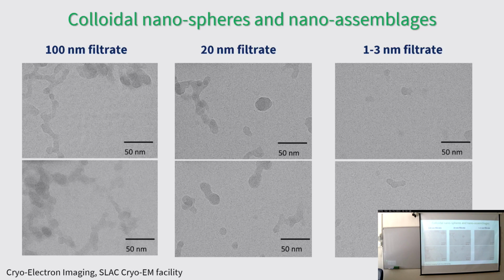Okay. So we characterized the colloids from the micron to nanometer scale, and we started with cryo-electron microscopy. I love cryo-electron microscopy because it just gives you a picture of your sample just as it is in the aqueous phase without any disturbances due to drying or filtering of the sample. It's quite difficult, I think, to see from where you're sitting, but we did identify all these spherical blobs in a variety of shapes and sizes. You can also see elongated structures of these colloids that seem to be made out of multiple spheres, sort of these nano assemblages. And addition of a smaller filter size of 1 to 3 nanometer validated that the colloids are indeed mostly larger than 1 nanometer in size.